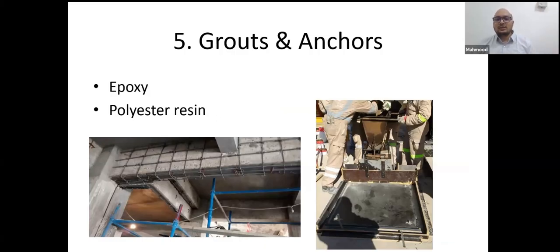Epoxy comes in a cartridge, with base and hardener. You can just apply it. It will come out mixed from the static mixer, and you can fill the drilled hole and fix the rebar according to the requirement. While grouting the epoxy, you will put a hopper to maintain the hydrostatic pressure. There is an epoxy grout below the base plate of machineries to withstand heavy, high dynamic load.